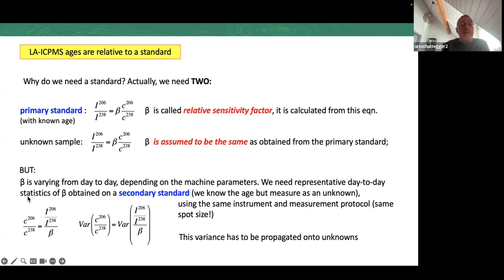And that means that from this equation, we can calculate the variance. So the variance in our intensity ratio normalized by the beta is equivalent to our variance in age. And this variance is also applicable to our unknowns. That means this variance has to be propagated onto our unknowns.